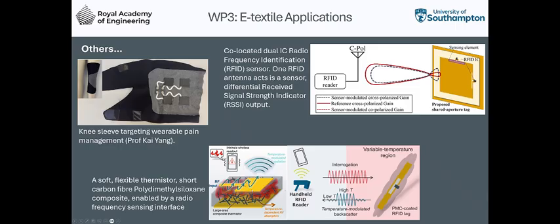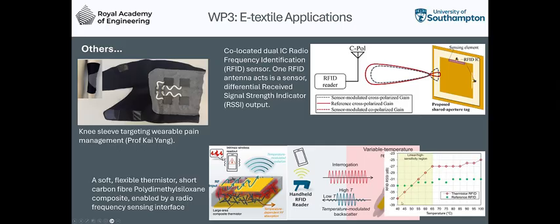In this case, we've added an antenna to a thermo composite material that changes its dielectric properties with temperature. And simply using an RFID reader, you can wirelessly measure temperature over up to 65 degrees. It works very, very nicely. So no electronics and no battery needed.